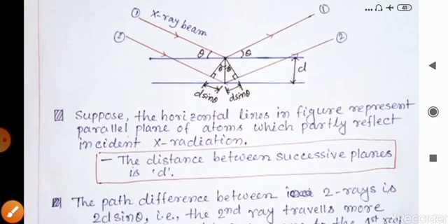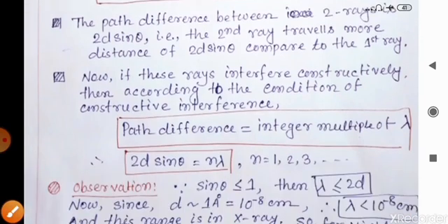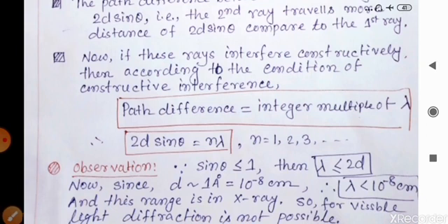The wavelength of the incident beam of light. So the path difference between the two rays, 2d sin theta, must be equal to an integer multiple of the wavelength lambda. This is the condition for constructive interference, in other words the condition for the bright spots in the film.